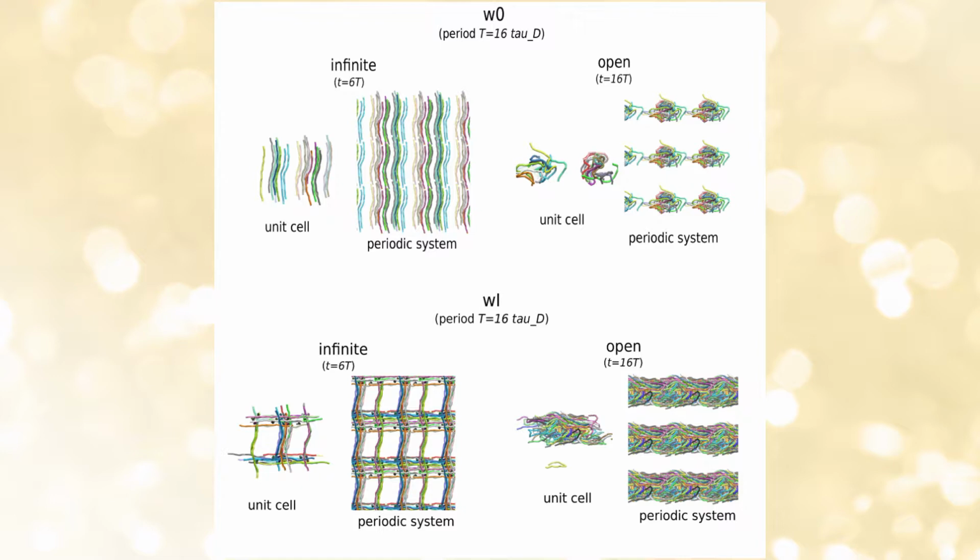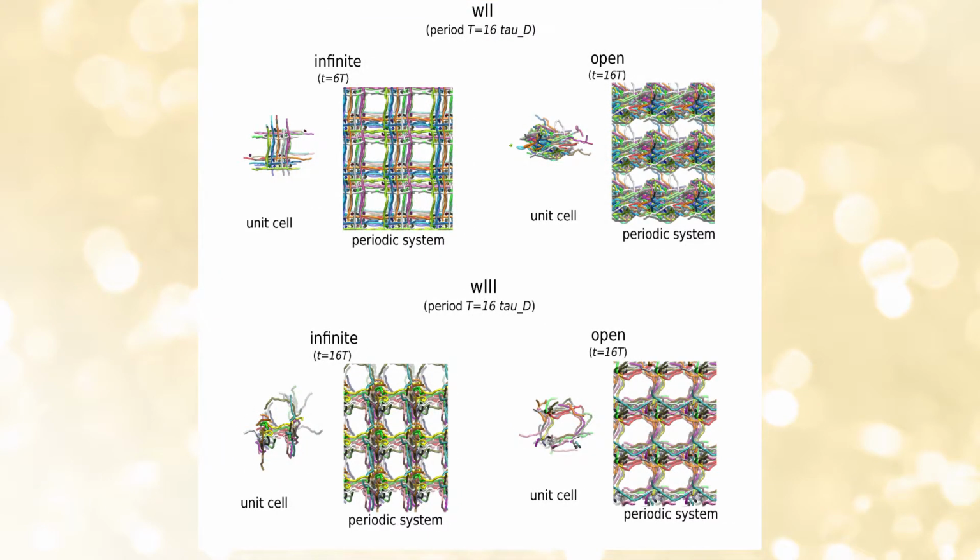The open systems rearrange a lot, but as we increase the complexity, there is more and more propagation of entanglement. If you look at the first one, it forms just blobs, and actually they're not entangled, they are all separated from each other, just going closer together. The other one creates tubes of things that are all interlinked. This one tries to propagate entanglement now in 2 dimensions. It forms layers of entanglement. And the third one now has entanglement going in all 3 directions.